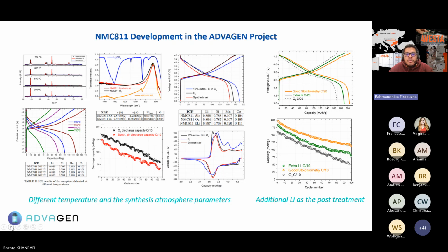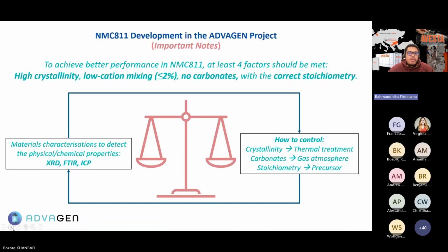But once we involve the 10% extra lithium and also oxygen, then we can see the balance between both. And here we also see that additional lithium as post-treatment can give NMC 811 an ideal capacity beyond 200 milliampere hour per gram, with quite sufficient cycle stability. So in this project we also develop NMC 811 based on the consortium trials.